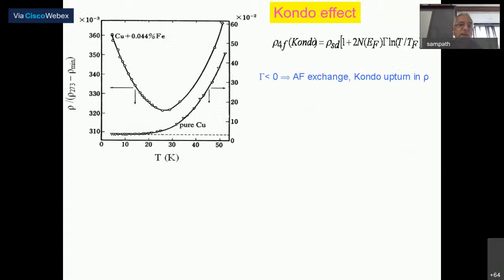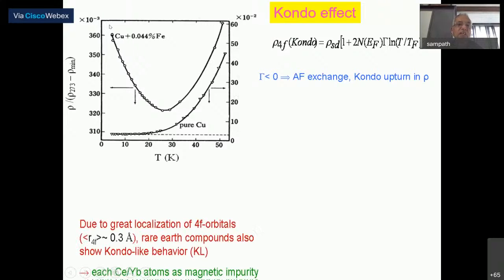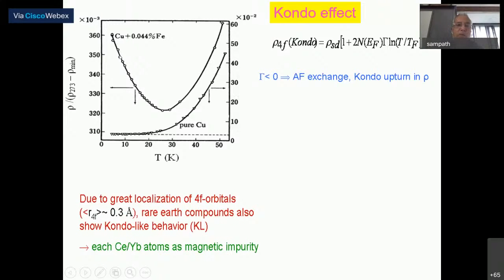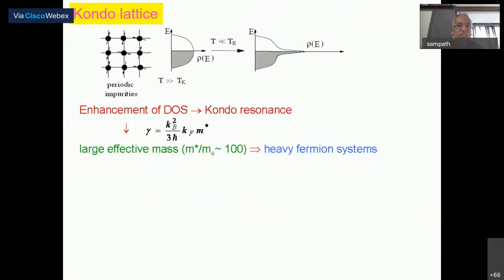So the well-known Kondo effect was first observed for iron impurities in copper. Instead of seeing a normal copper-like behavior, you could see an additional contribution at low temperature, which varies logarithmically with temperature. This is called the Kondo effect. In other words, the Kondo effect is defined by a system in which your electrical resistivity exhibits a minimum in its temperature dependence. So this is a typical behavior of the Kondo effect, which varies exponentially as a function of exchange interaction strength.